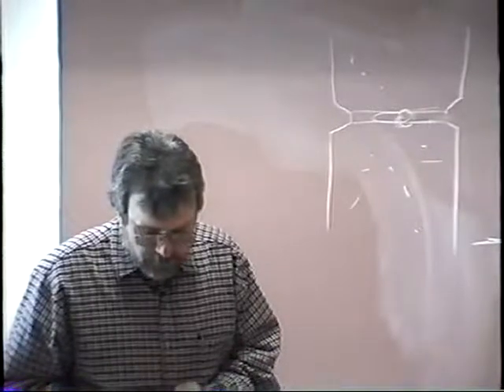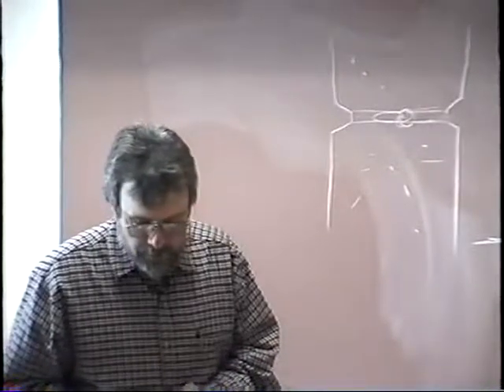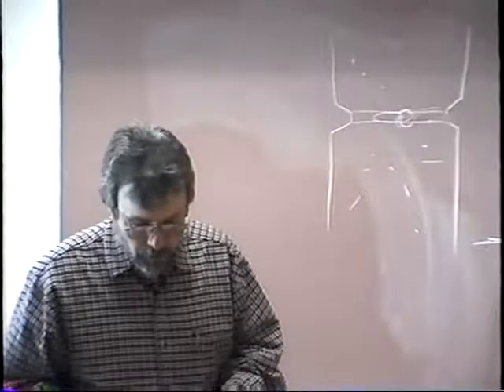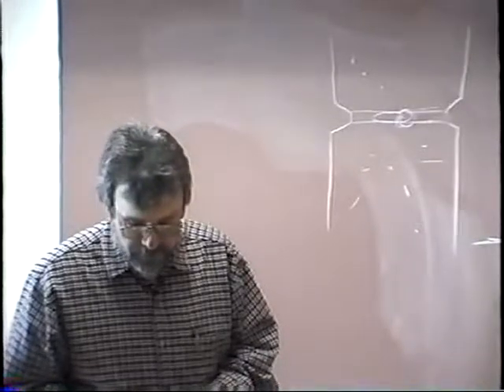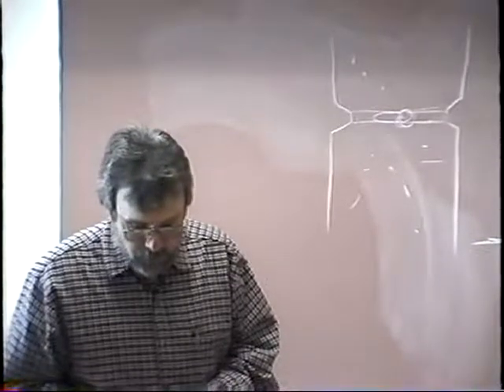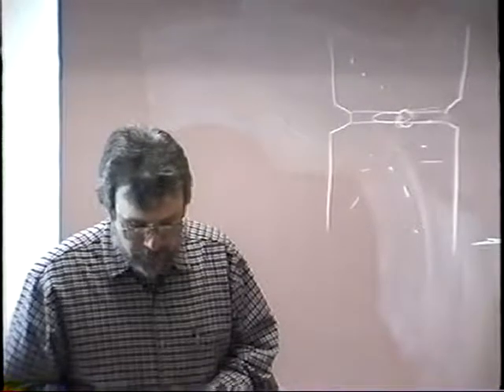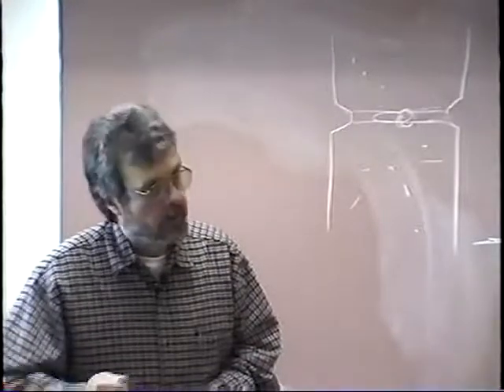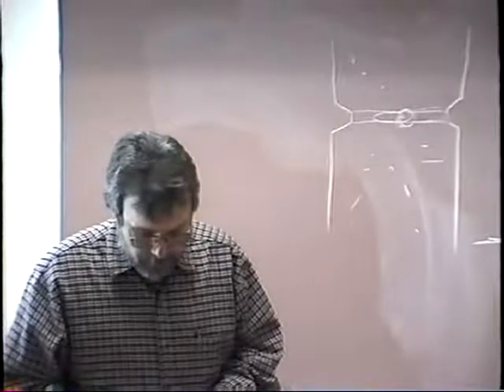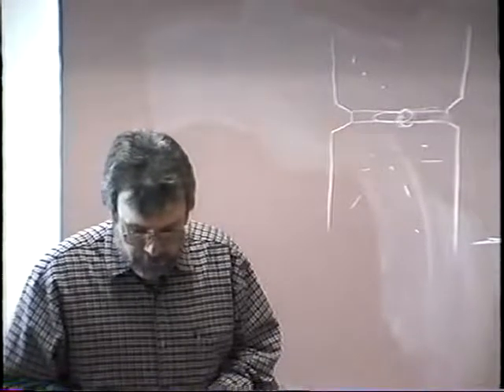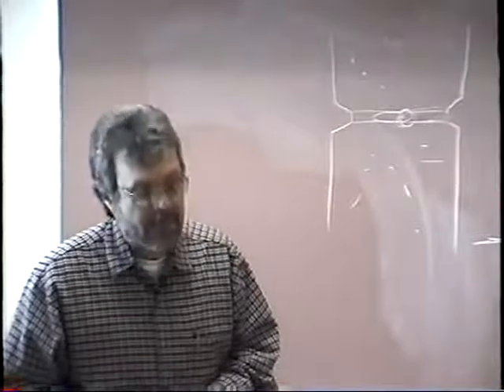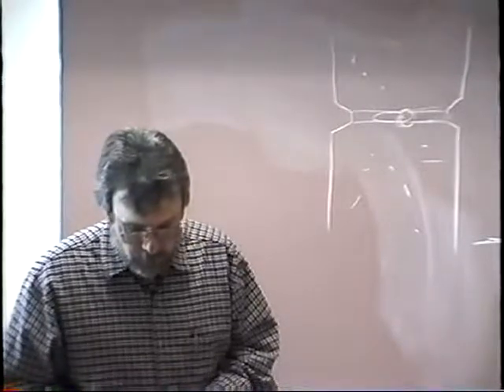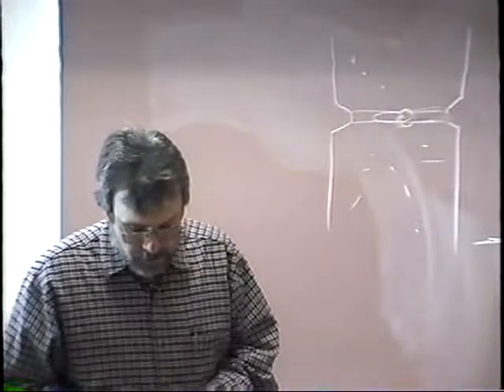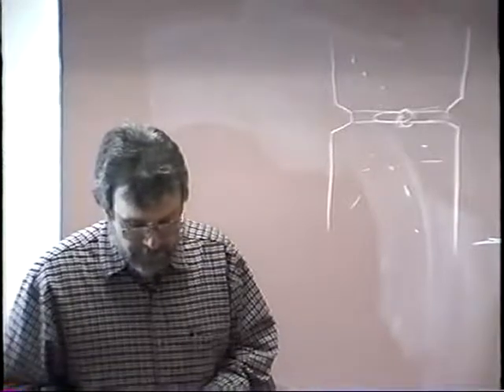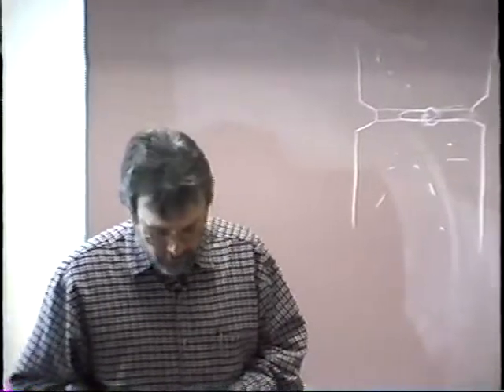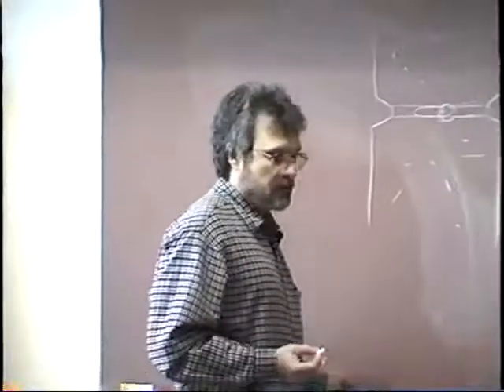Dropping down to the second paragraph from the bottom, it says the object of whipping is, of course, to control the pool of molten metal and prevent it from sagging. The length of stroke should be about 1 or 2 electrode diameters. So you're not going out very far at all. Dropping down a little bit further, it says, while welding the root bead, attention must be paid to the keyhole and the molten metal. If the keyhole shows signs of increasing, the speed of welding should be increased slightly and the electrode angle decreased slightly. Why would he want to decrease the electrode angle?